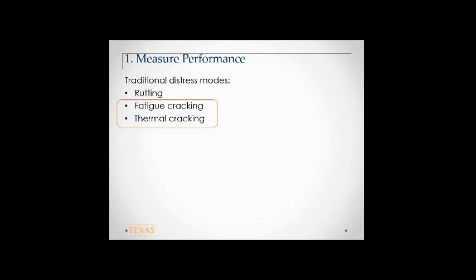But if you have an extreme cold weather outside, the material is shrinking or trying to shrink, it's building up these thermal stresses, and it is ultimately the binder that has to relax and relieve those stresses. Because if it cannot do that fast enough, the stress buildup will be so high that it's going to crack. Okay, so that's again why binder is more responsible in these two areas.